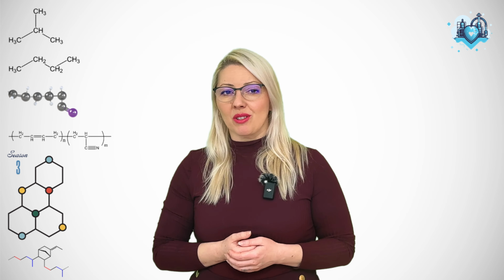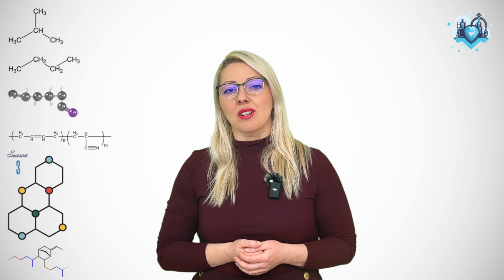And a short but important clarification. When we talk about oil appearing on the surface, we are talking about bleeding or sweating, which refers to liquid migration. When solid additives like waxes or sulfur move to the surface, that phenomenon is called bloom. Different mechanism, different physics. Today's episode is strictly about liquids.